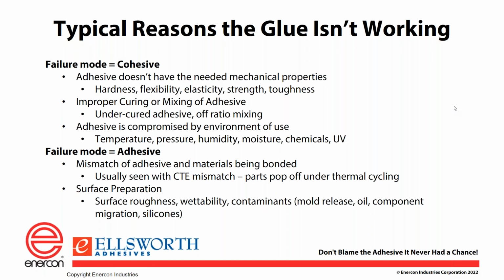Another common reason you would have cohesive failure is that the adhesive itself is fine, but the environment of use creates changes to the material. So things like wide swings in temperature, pressure, humidity, moisture, so actually contact with water, other chemicals. So for instance, if you're in an automotive application and the material is subject to things like greases and fuel or exposure to UV, all of those things, depending on the type of adhesive you choose, may compromise the performance of that adhesive. So up front, you would want to know what the environment of use is and select the adhesive based on how robust it needs to be in that environment.